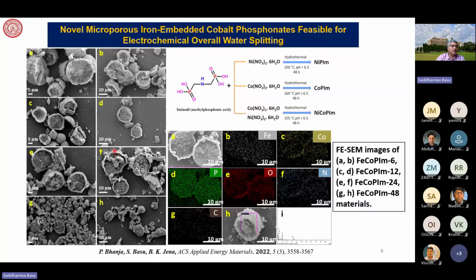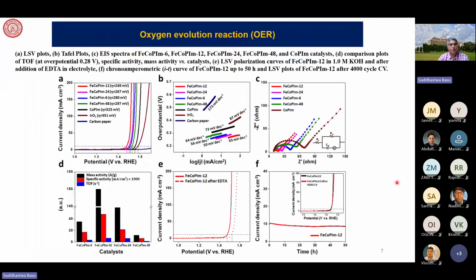So this half-sphere kind of structure that you get, and then we have done EDAX to show that you have all the material that we started with and we wanted to have: iron, cobalt, or phosphonate. Not all of them we made, but the one we got the best results is iron, cobalt, phosphonate, and the best one we got at about 24 and 12 hours of refluxing, and that is being captured here in the oxygen evolution reaction, as we are showing you here.